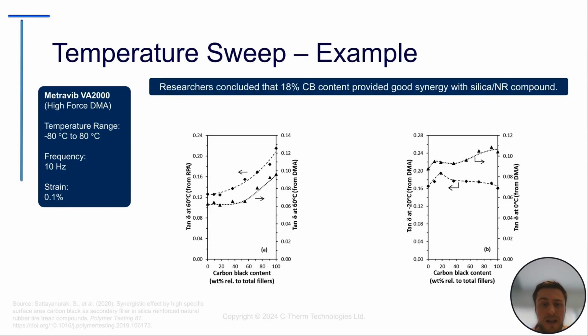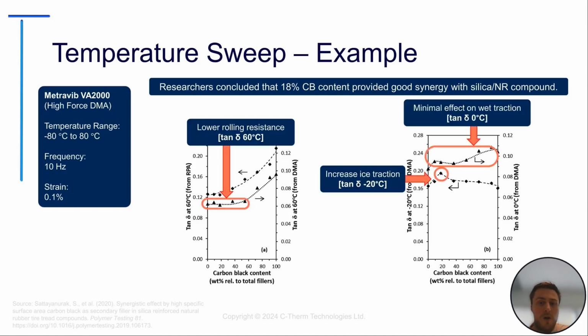And the researchers were able to conclude that 18% carbon black content provided a good synergy between the silica and natural rubber compound here. And I'll highlight how they came to this conclusion. So they plotted their tan delta. The plot on the left here is the tan delta value at 60 degrees Celsius versus carbon black content. They're able to see that lower carbon black content provided good rolling resistance, or lower rolling resistance, I should say. And then measuring the tan delta at -20, they're able to see that there was a peak in ice traction performance with 18% carbon black content. And then they noticed that the carbon black had a minimal effect on wet traction. So they were able to conclude that 18% carbon black was the optimum content for their material.